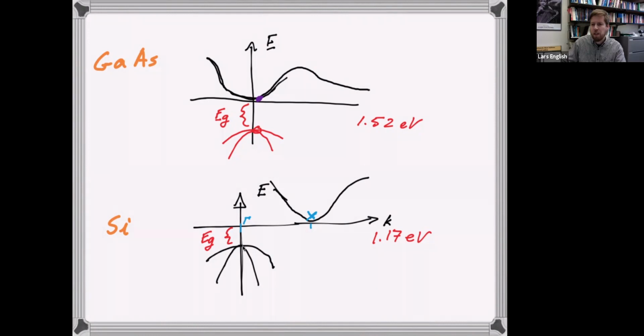We said there the top of the valence band is at the origin, again in k space, a point sometimes referred to as gamma, but the bottom of the conduction band is at a different point in reciprocal space, at a point sometimes labeled X. And so the band gap, the difference between the top of the valence band and the bottom of the conduction band, is about 1.17 electron volts at low temperatures. And we see that goes down just a little bit, to 1.12 electron volts at room temperature. So that's the effect we were talking about earlier. But that's not really the point here. The point is that these two important points in k-space are different, right? So they're not facing each other here. So what's the consequence of that? Well, first, some terminology.